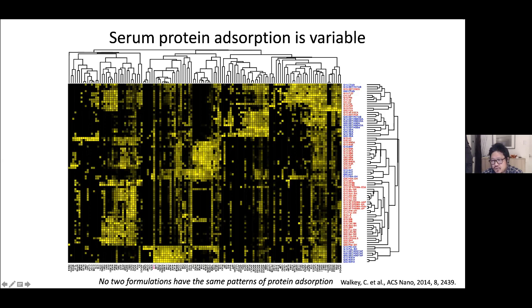What was interesting was not the specific proteins adsorbed, but the patterns of proteins adsorbed. We found that no two formulations yielded the exact same pattern of proteins on the surface, even though all particles were synthesized and characterized in the same timeframe. This tells us something very important: when you make a formulation that isn't standardized, you may have different proteins adsorbed to the surface, which can have downstream impacts you may not be aware of from the outset.